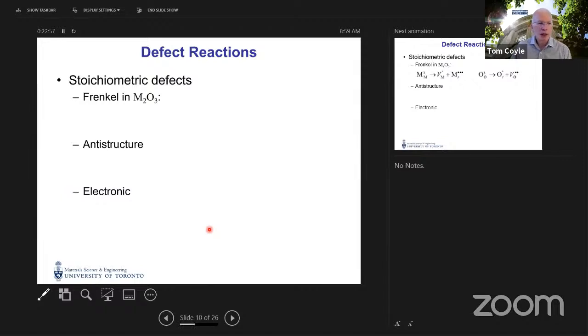So we can look at other defects in the same way. The Frenkel defect: one type of Frenkel defect is a vacancy on the cation site. So a cation site occupied by a cation with no effective charge becomes a vacant cation site with a relative charge of -3. And we need to maintain charge balance. So where did that cation go?